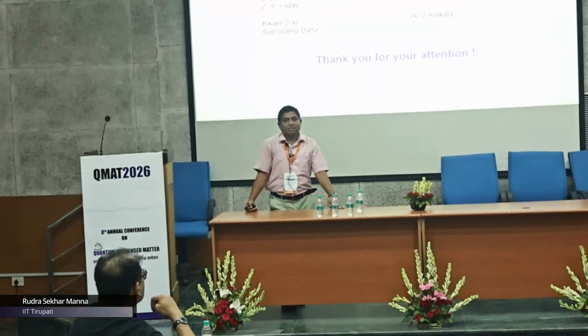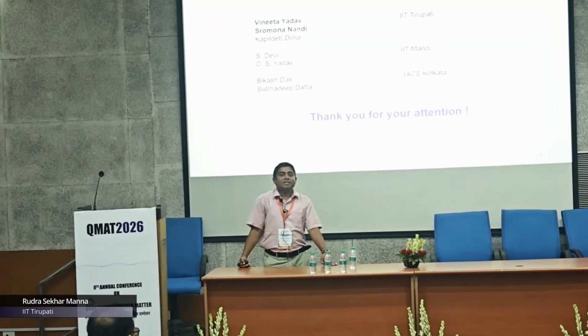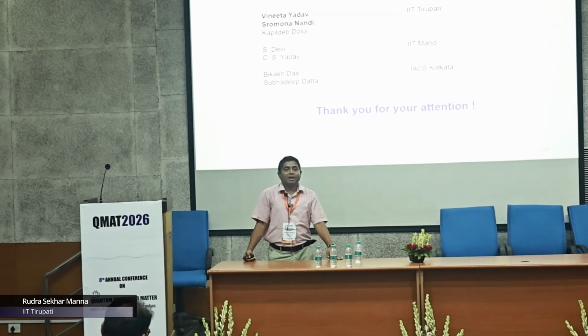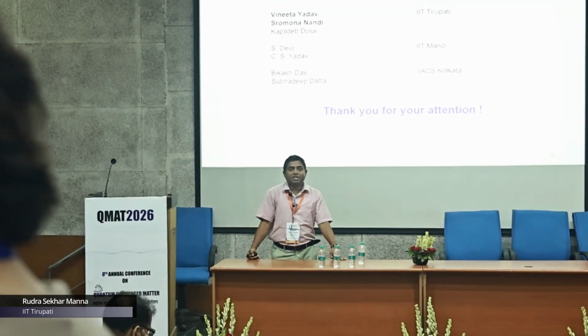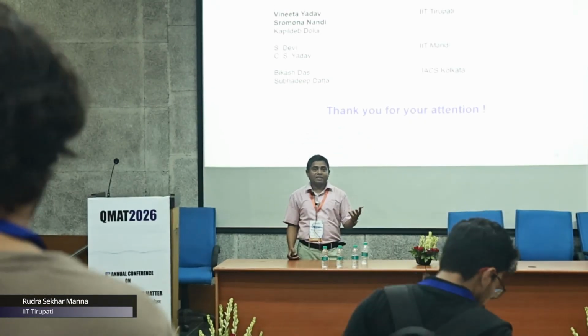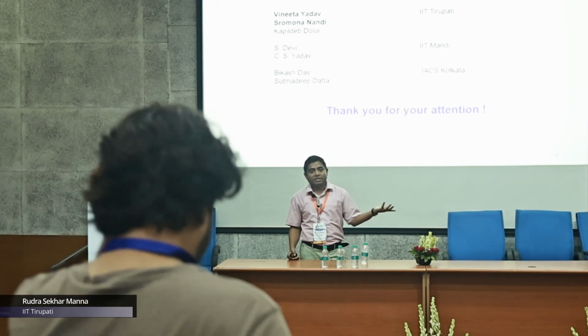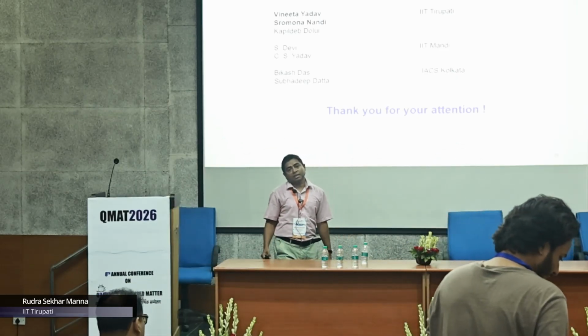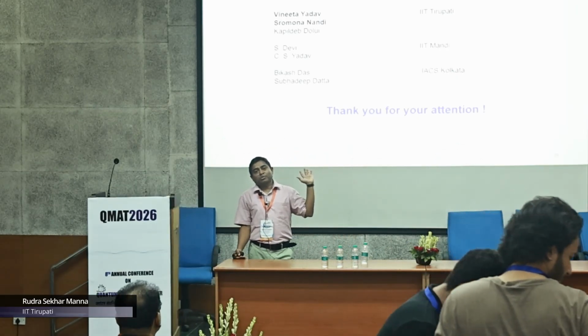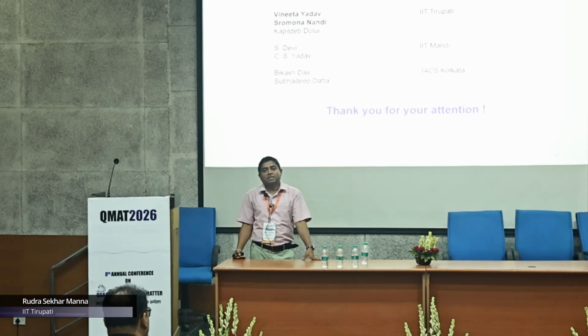Correct. That's a good question. Of course to go to that high pressure, like 40 GPa, it's a bit challenging. What we planned is not yet successful. What we are seeing is that if someone could do high pressure synthesis, that means you prepare the material at high pressure, there are some techniques available, then you can do ambient pressure resistivity, let's say. But we haven't done so. One measurement which I showed at x equal to 0, we could go up to 2 GPa, but that is much less than what is needed.